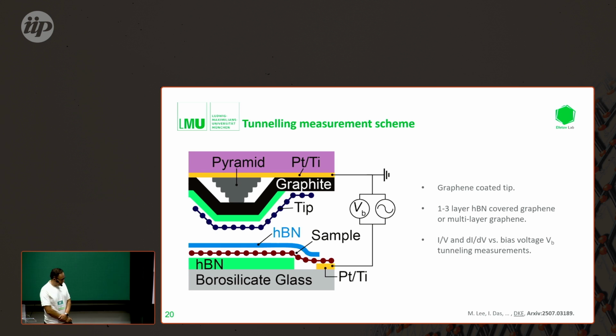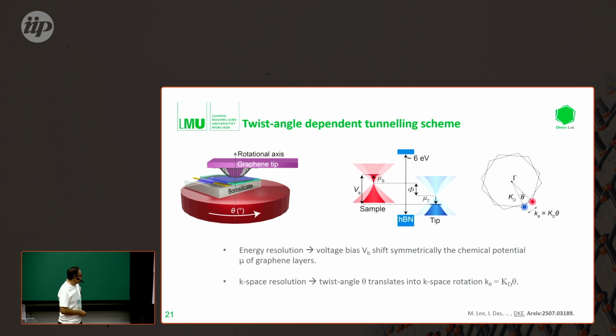The measurement scheme that we use is tunneling spectroscopy. The tip has this geometry: we have a pyramid, we have a cushion layer made out of graphite and hBN, and we have the tip covered with graphene. The substrate is hBN-covered graphene as well. What we can do is apply a bias voltage across the tip into the sample and measure a tunneling current. Of course, we can also rotate the substrate, and continuously map out the tunneling current while we're rotating the device.